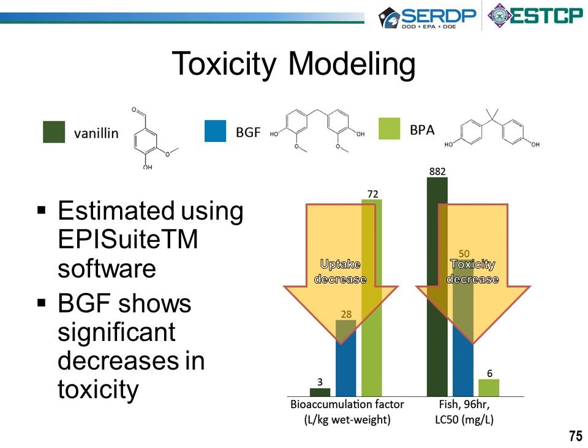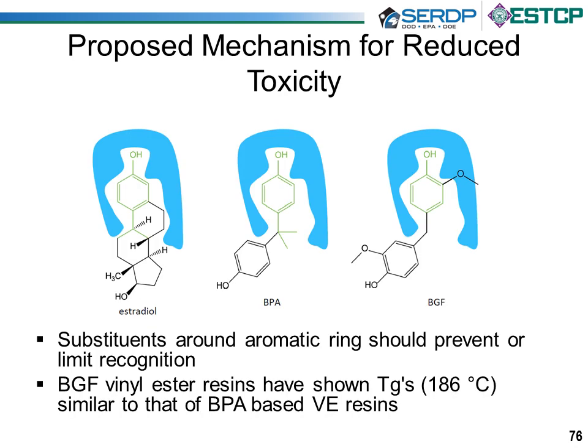The reason we believe this is the case is that these molecules react with enzymes in the body, and BPA basically mimics estradiol, but BGF, because of that methoxy group, can't really fit into the same space as the BPA does, and therefore should reduce the toxicity. Other things about these materials is we found that they have very good Tgs, similar to that of BPA-based vinyl esters, and the epoxy resins that we made from them have been excellent so far as well.